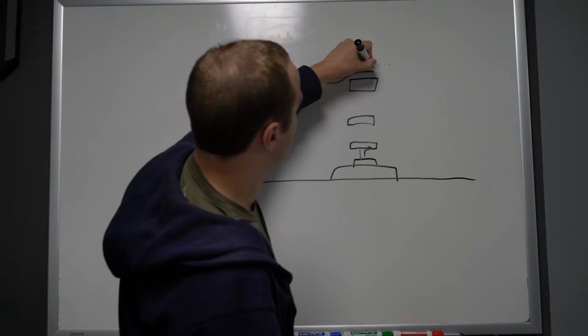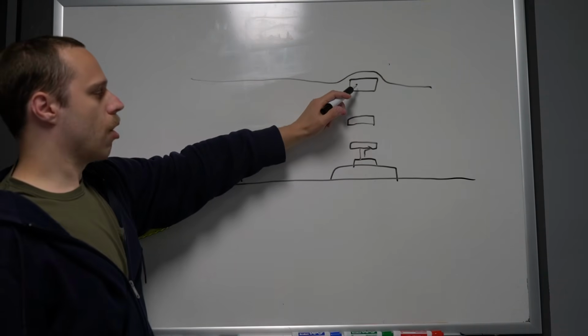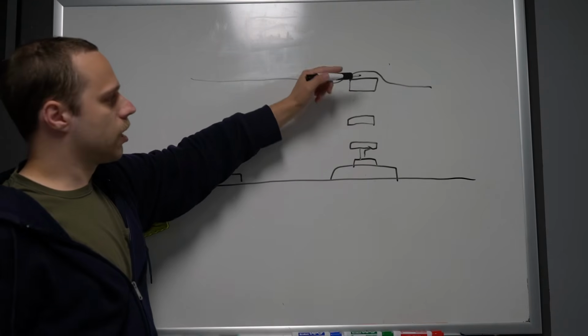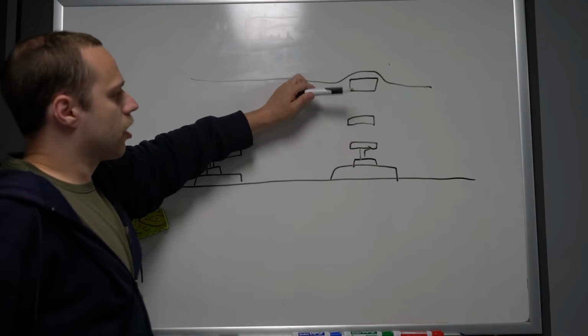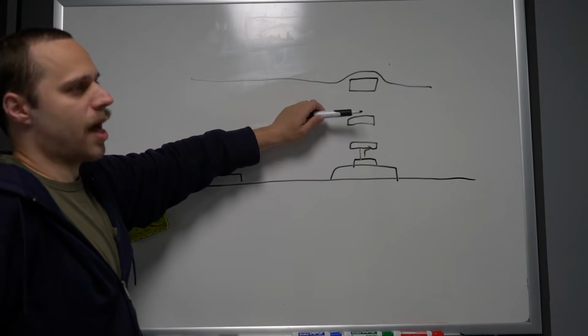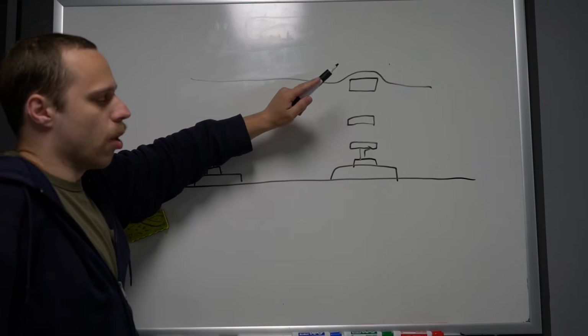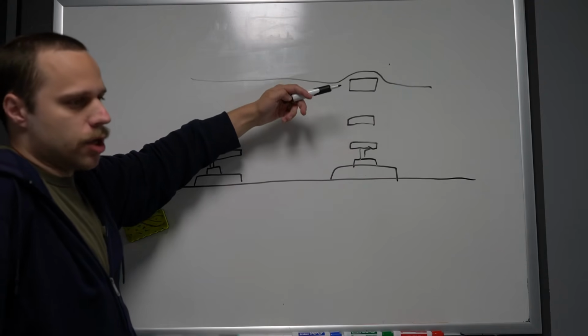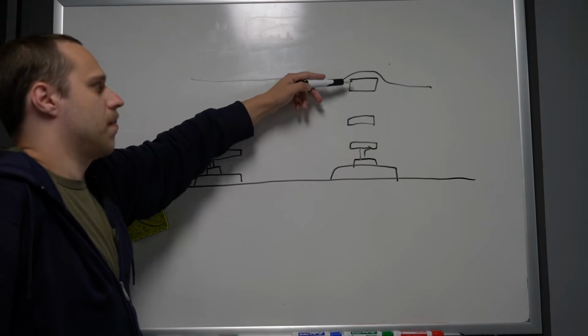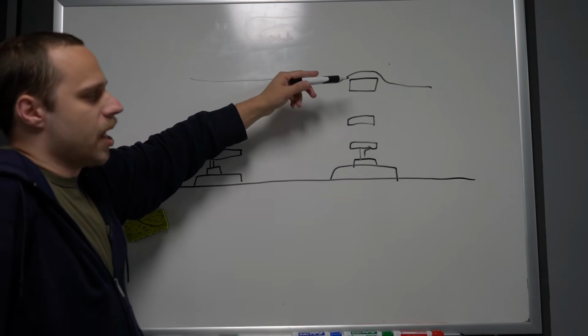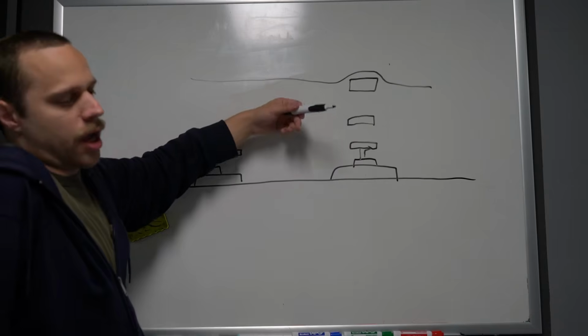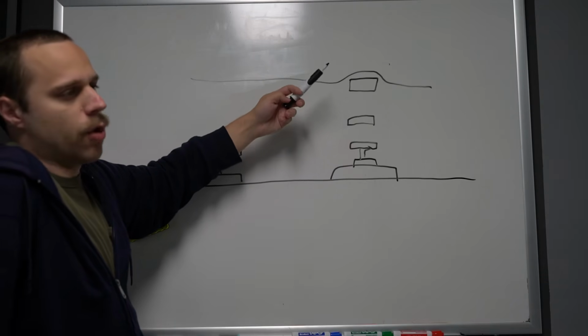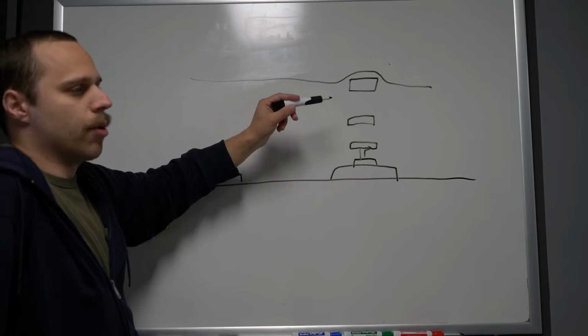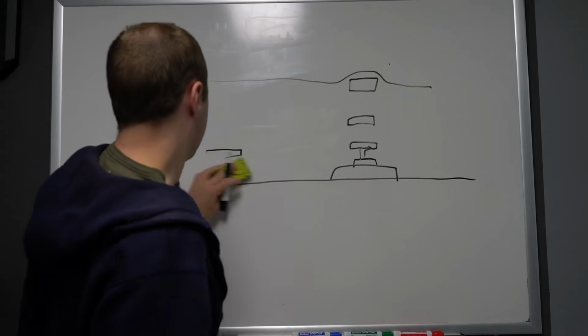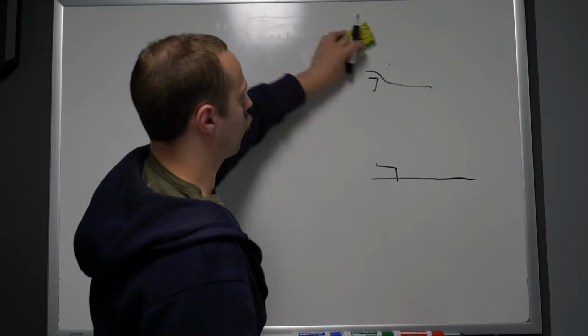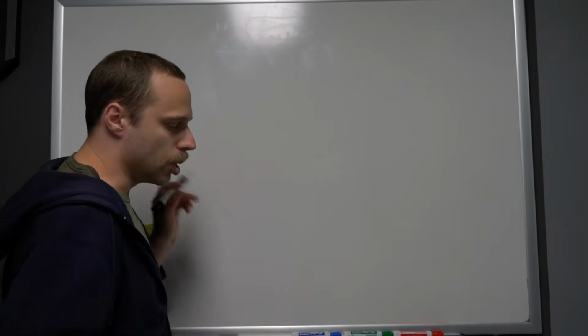It's actually going to be kind of more like that, where it flows over the surface of the top metal layers. The lower layers are planarized. The surface of the wafer is polished flat in between. This is done both for lithography reasons, so that the depth of field of the imaging system isn't affected by height variations in the surface. And on more modern devices using copper metallization, this is also an actual fabrication step, because copper is not possible to plasma etch. But in this case, we know from the cross-section as well as just from the general age of the device that this is an aluminum device.